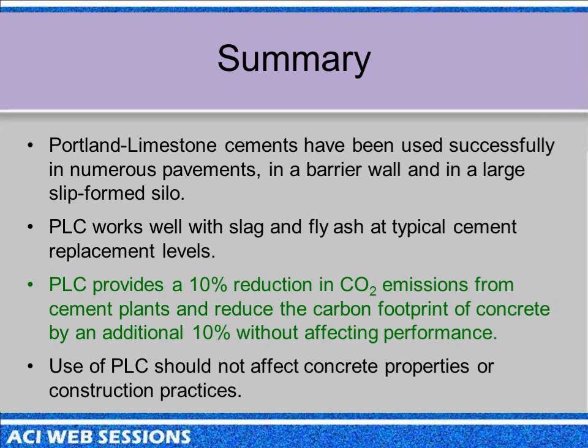So, in summary, they have been used successfully in a number of projects, pavements, barrier walls, and I showed a slip-form silo. But there's a lot of other applications they've been using in a lot of precast products. It works well with slag and fly ash at the normal replacement levels that the ready-mix industry is used to using. It's pretty transparent to the users. They shouldn't see a difference, except perhaps in the finishing, because it actually finishes better because of the extra fines from the limestone.